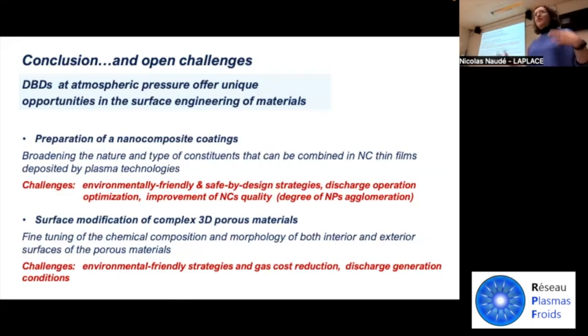But in principle, it's possible. With the discharge modulation and high flow rates, in which the plasma uses a very small amount of the dispersion, you are able to obtain uniformity. There are other drawbacks, in that you don't utilize all the precursor, but in such a way you can mitigate these problems on the surface. And what about the post-discharge? The post-discharge, yes, there is some collection in the post-discharge region. And typically, of course, you mainly deposit particles. In the post-discharge, you really observe a greater contribution of nanoparticles.